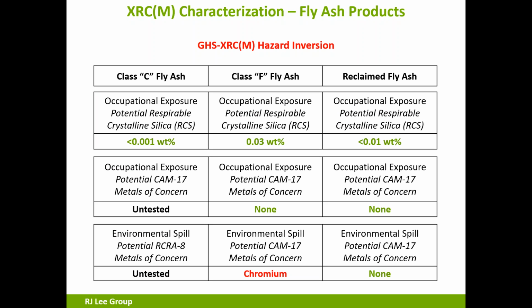So in summary, the Class C occupational exposure was less than 0.001. As you remember, we had Raman data for that. We did not have data for the metals on that product. Class F, 0.03 weight percent. It clears for GHS on the crystalline silica. Occupational exposure was none. It did have a chromium metal of concern that we would want to look at a little bit closer. The reclaimed fly ash was obviously non-detect for respirable crystalline silica. There were no metals of concern for occupational or environmental, and that product has cleared.